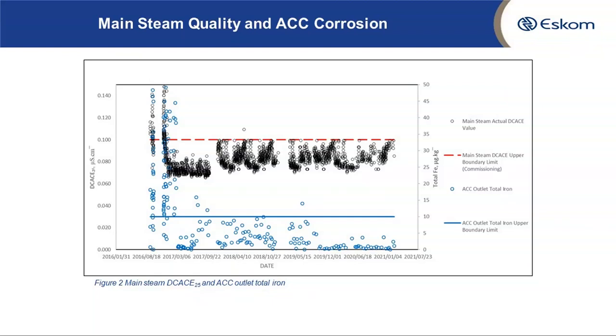Again, you will see that during the early operation or commissioning, iron was very high, the unit is very dirty, but over time, the total iron as measured at the ACC outlet decreased and was well within the boundary limit. The total iron concentration was higher, but largely within specification when the unit was on AVTO, and showed further improvement when the unit was on OT. If you look further right, that is when the unit was already on OT or AOT. Very low total iron levels were measured at that period. This information is consistent with the Dooley-Aspden pH versus iron relationship that Dr. Dooley has just shared with us in his presentation. If you can move to the next slide, Scott.